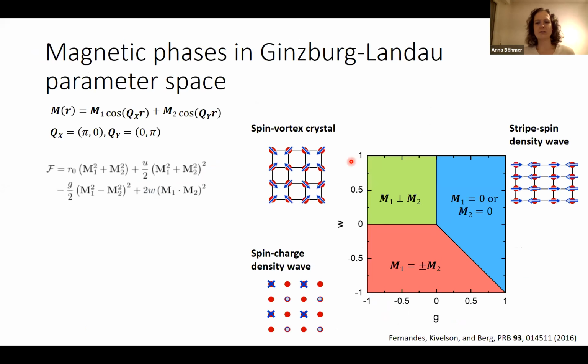And to give an overview and some systematics, let's go to some theoretical description. To describe this order, and that was done long ago, we can use two spin density waves, one with two equivalent wave vectors and two different order parameters, M1 and M2. To recover the stripe phase, one of these order parameters is set to 0, and then we get our stripes. But in the Ginzburg-Landau approach, there are different coupling parameters, and in the phase space of these coupling parameters, we find different magnetic orders as well.